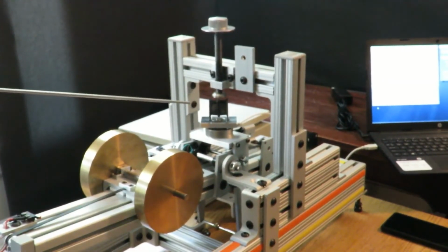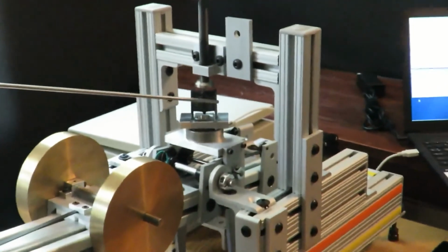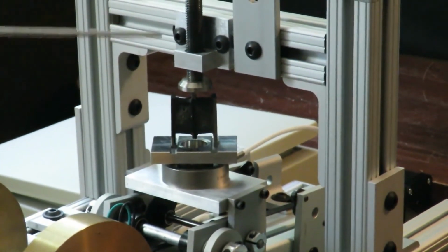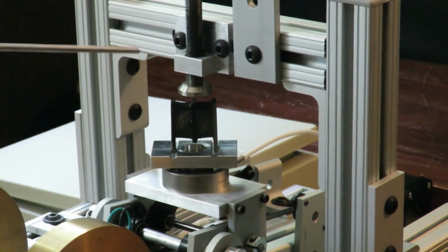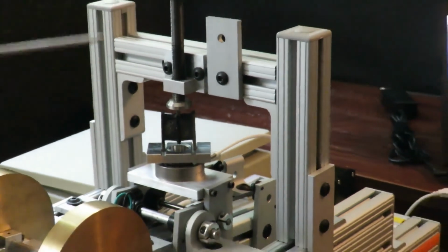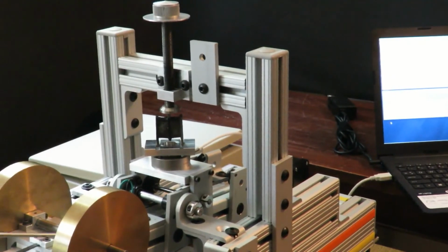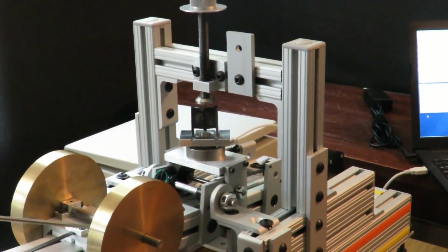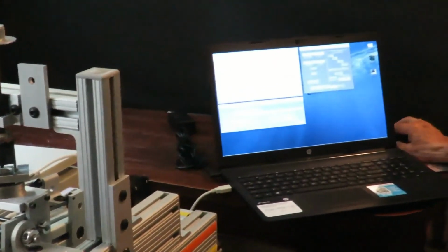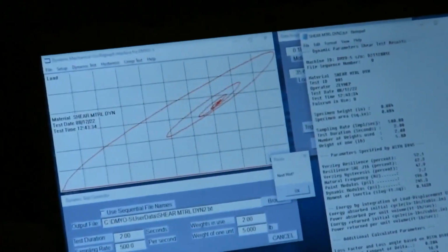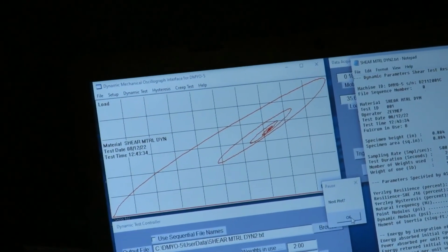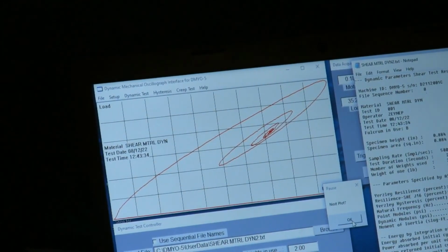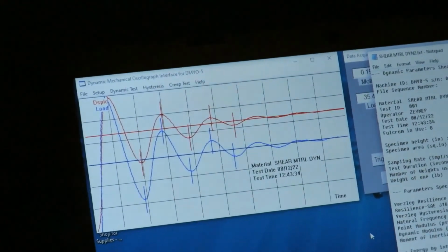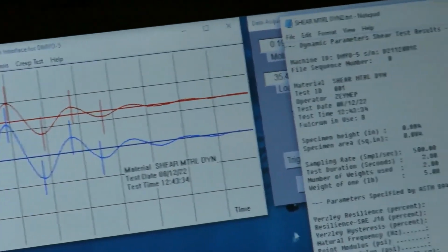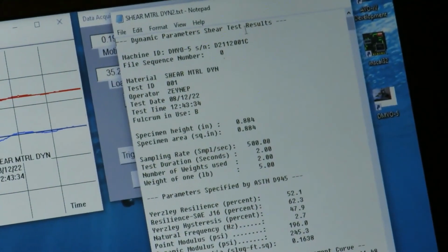The shear specimen is composed of 2 rubber components bonded to 3 steel platens, and the forces are perpendicular to the beam. So in this case we have a shear specimen which we will run a dynamic test on, and as we can see there are 2 weights on the traveling table, and that is ready to run now. The first plot is our load versus displacement plot, and it's very clear. And then the next one is load displacement against time. Tabulation is on the right, and we see outputs from there as we did before.